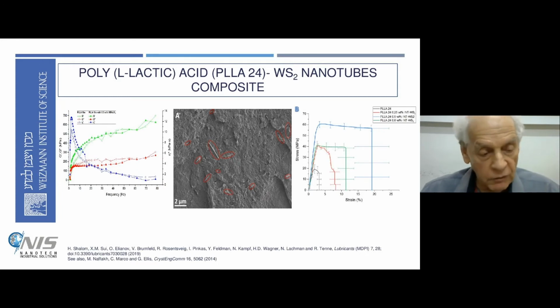This is a real important finding, because first, it's very easy to disperse these nanotubes into the polymer, which is unprecedented—you don't find it with other nanoparticles. Secondly, it reinforces the polymer dramatically. A third important property for any application is that these nanotubes are found to be non-toxic, so they are completely biocompatible. At least so far there hasn't been an in situ experiment on a human being, and it will take time until we can do that. But we are getting closer to showing that these materials are very useful for many medical technologies, and that's why there's so much interest in these materials, also from industry—because polymers are used everywhere.